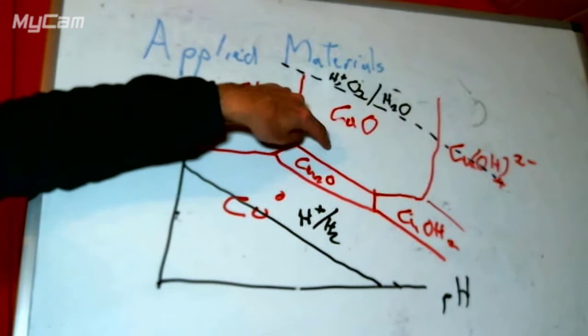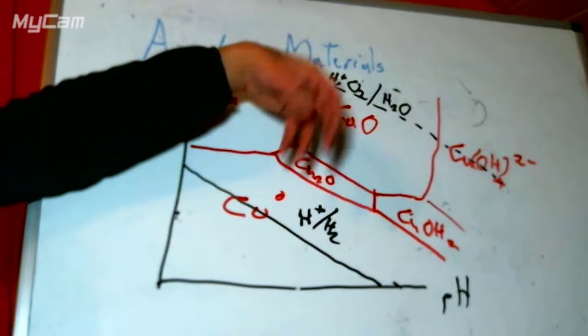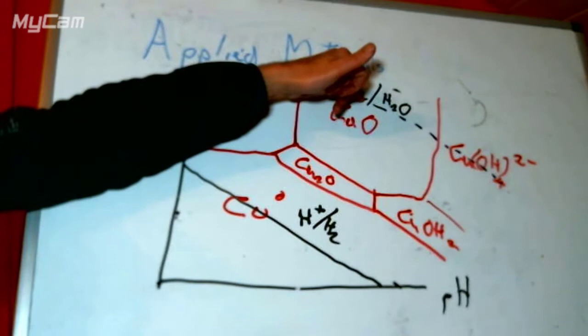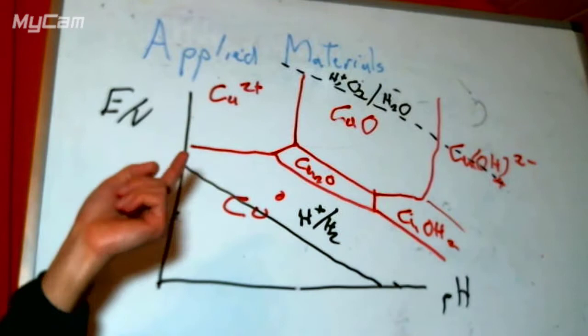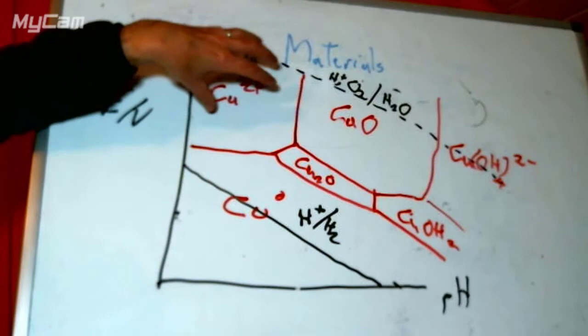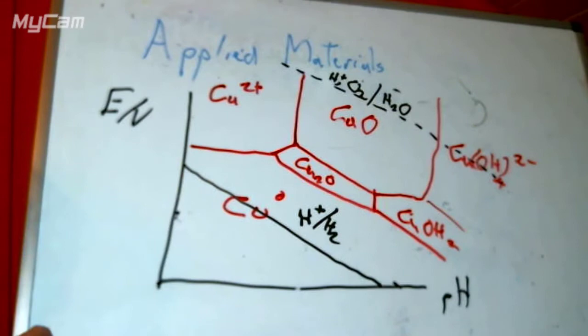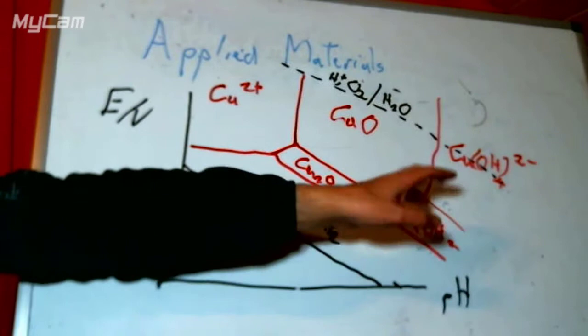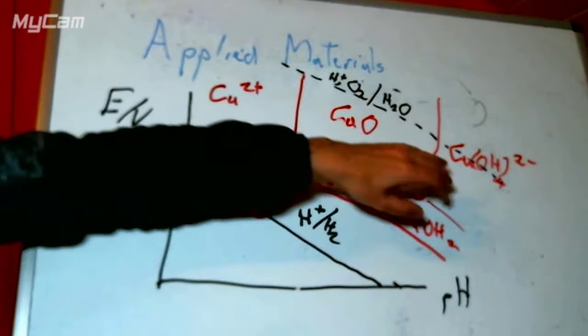If we make it more positive, it's going to motivate more reaction, so the copper oxide layer will be thicker. If we make it very acidic, we can make copper²⁺ ions directly. If we make it very basic, we can make cuprate ions — copper hydroxide ions — which are the dark blue ones you might have made in chemical tests. Those are the weird copper(I) salts as well at intermediate oxidation.